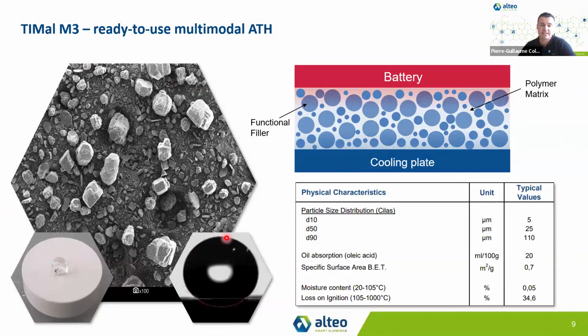So on the left, you can see a SEM picture of our product, including different size of particles. And at the bottom, you can see some example of hydrophobic surface treatment, which provide a nice lotus effect when we just put a drop of water into a pressed powder. So our product is a multimodal ATH. So it has an intrinsic bulk thermal conductivity of 20 watts per meter Kelvin. And also it's considered as a soft filler with Mohs hardness of around 3.